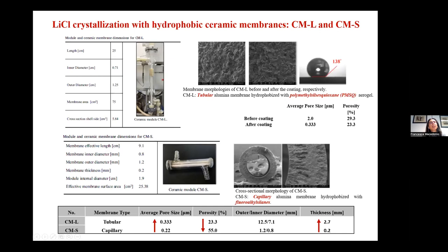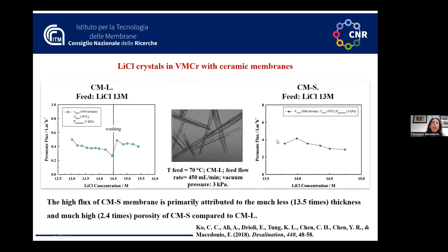The first one is a tubular alumina membrane hydrophobized with polymethyl silsesquioxane, and also a capillary alumina membrane hydrophobized with fluoroalkylsilane. In both cases, we were successful in the crystallization of lithium chloride. Of course, considering that the two membranes are different not only in diameter but also in porosity, what we observed was that the membrane with higher porosity, the capillary one, had a higher flux. But in any case, both membranes were useful for the lithium chloride crystallization.